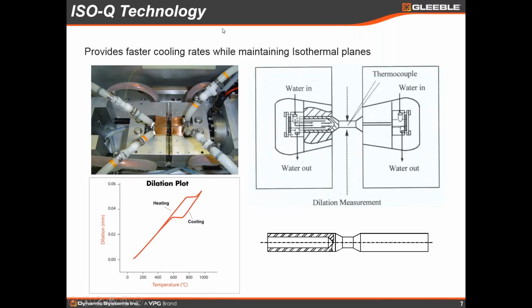With the Gleeble, we even have one more trick that we can get even faster cooling rates while maintaining that isothermal plane in the center as we cool the sample. This is a picture of what we call our IsoQ Quench setup. That stands for isothermal quench technology.